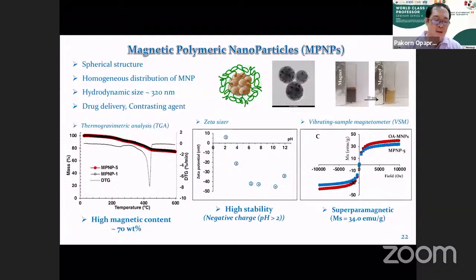So how do we know that? When we measure the content of the magnetic nanoparticles using TGA, we can see that the magnetic content in the particle is at least 70%. This ensures that the material has very high magnetic properties. And if you look at this TEM picture, you can also see very clearly that the black domains are magnetic nanoparticles that are evenly distributed in the polymeric particles.